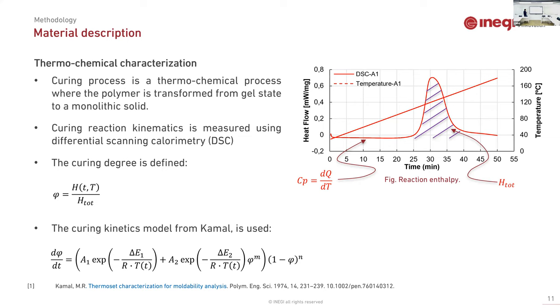Taking this into account, we can define the degree of cure as the ratio of how much energy the material has released to the total energy that the material needs to release to be completely cured. This quantity goes from 0 to 1. 0 is not cured, 1 is completely cured.